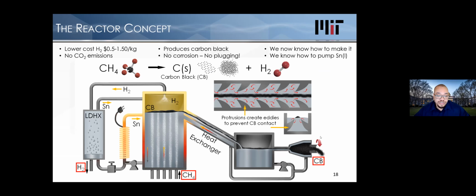So what you can do is you can take liquid metal tin, let's say you've got a big vat of it at 1400 C, bubble up methane through it, and inside the methane bubble, the gas is going to heat up to 1400 C, then the reaction is going to take place. It's going to decompose, that bubble will now be filled with hydrogen, and you'll get carbon particles inside. Now, when that bubble reaches the top surface of the tin, it'll open up, the carbon will rest on the surface, and the hydrogen will go out, and you can pull the gas out separate.